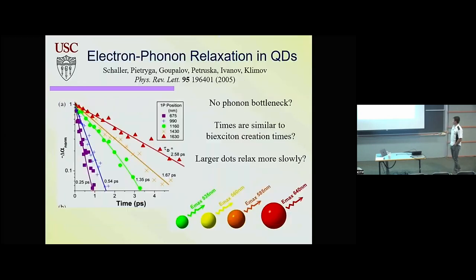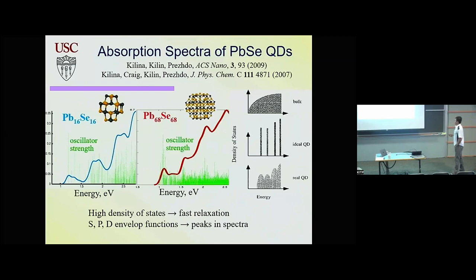But in those days, this is experience from Viktor, what he saw is the opposite. First of all, the timescales were pretty fast. And second, the relaxation was actually faster for smaller dots. So smaller dots, larger gaps, but the electron-phonon relaxation, energy losses to heat are faster. And this is all because the effective mass model gives you some envelope function, gives you optical selection rules, SPD type states, etc. But there are many, many individual states under each envelope function.